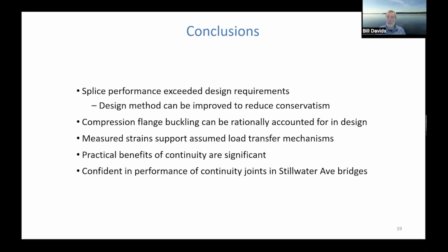Compression flange buckling, that did occur, and that has to be accounted for in design. It's another limit state you've got to look at. The good news is we can rationally do that with existing models. The experiments agree very well with what they predict. All our measured strains supported our assumed load transfer mechanisms. The practical benefits of continuity are potentially very significant.